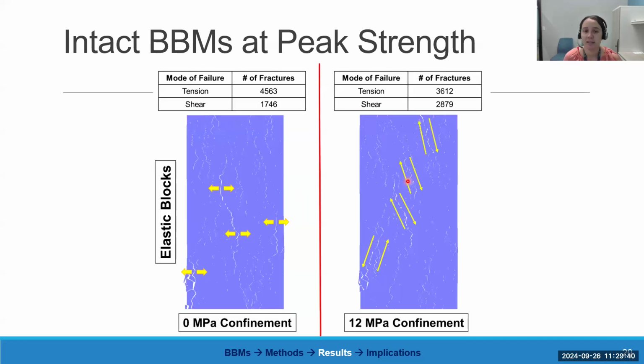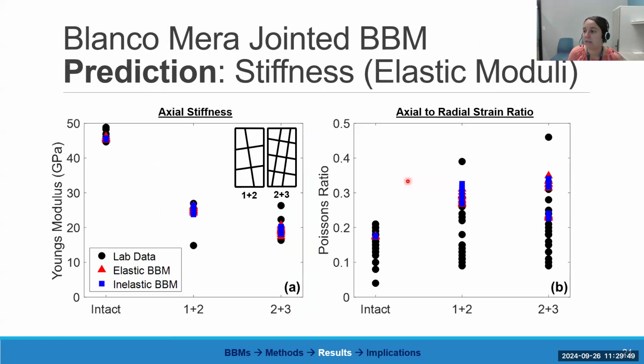Okay, so in these last few slides, I just showed you all that the calibration I did was good. So now that I calibrated this intact model, the next step is to add the 2 different fracture geometries, so the 1+2 and the 2+3. And I ran these simulations without changing any of the input parameters from the calibration. So no adjustment of input parameters whatsoever. And now we want to see how these two cases of the jointed models behave and how they compare to the laboratory data of the jointed specimens.